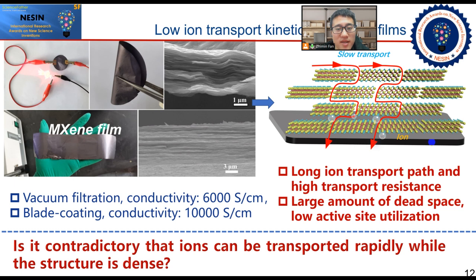The arrangement of MXene film sheets obtained by filtering or scraping MXene is extremely compact and has excellent flexibility. Like other two-dimensional materials, MXene also has a high aspect ratio, which can significantly reduce ion mobility and decrease capacitance, especially for thicker electrodes, where this decline is more pronounced. In addition, MXene sheets face the disadvantage of restacking and aggregation, causing loss of active sites when building macroscopic films, which is detrimental to energy storage and conversion.